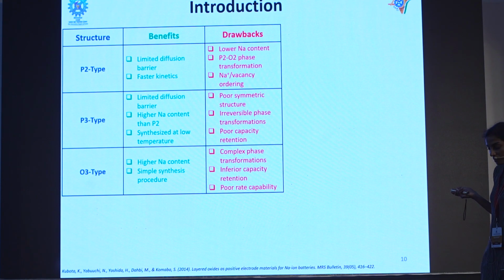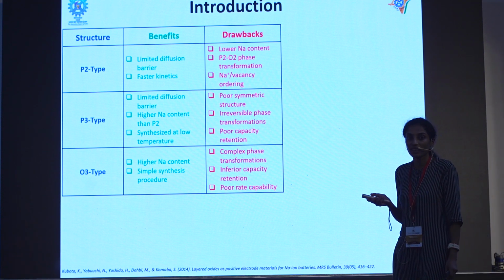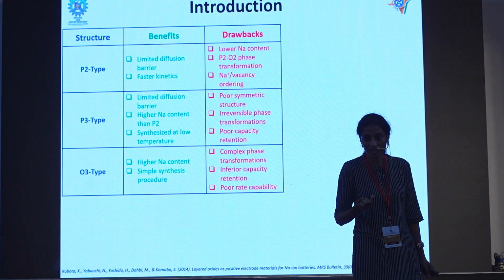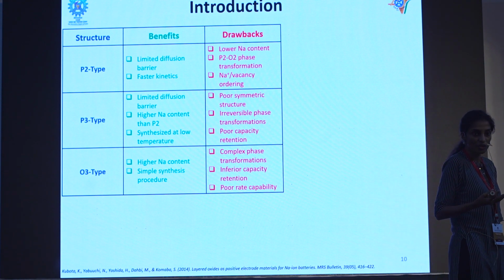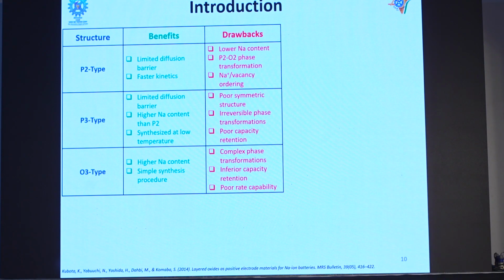The O3 type materials are much more attractive in terms of sodium content. And what is the relevance of sodium content? The more the sodium, the more charge it can store, the more capacity. But the major problem is it undergoes complex crystal structure transformation, or in simple words, phase transformation, which is not reversible. So we omitted the O3 type and we are focusing on P2 and P3 type in our work.